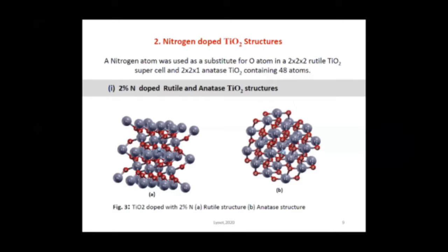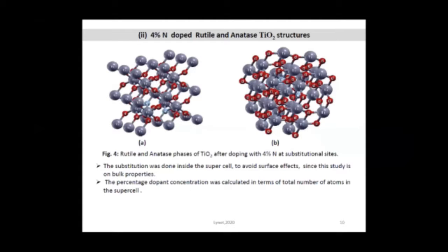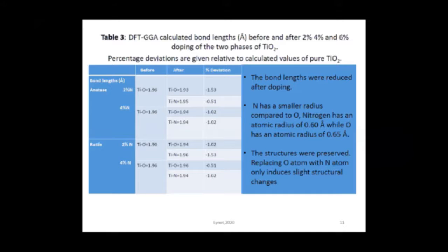The doping was done in a supercell, a 2x2x2 supercell for rutile and a 2x2x1 supercell for anatase. And we substituted nitrogen at oxygen sites, as you can see. So our first diagram represents the two structures, the anatase and rutile TiO2, doped at 2%. Then the next slide represents the two doped at 4%. The percentage dopant concentrations were calculated in terms of the total number of atoms in the system. That is how we achieved the 2% and the 4%. We tried 6%, we shall discuss what happened there.